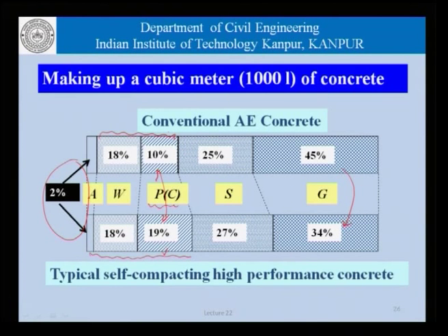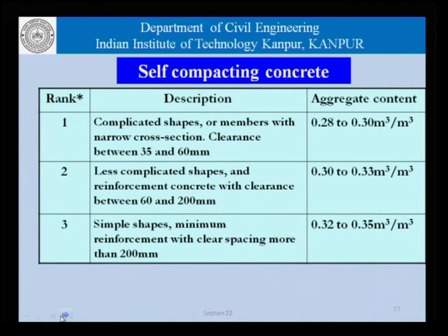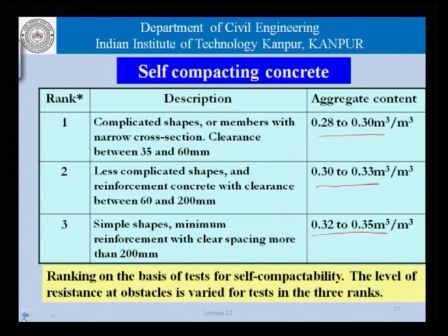compared to conventional volumes, and this is compensated or made up by the reduced volume of coarse aggregates, and that is something which we had talked about last time, and we had also seen this slide here which talks in terms of limiting the coarse aggregate content between 28 to 35%, depending on the complexity of the formwork or complexity of the member in which self-compacting concrete is to be cast. This ranking that is given here, rank 1, 2 and 3 for the aggregate content, is based on tests for self-compactability, and the level of resistance at obstacles is varied for the tests in the 3 ranks.